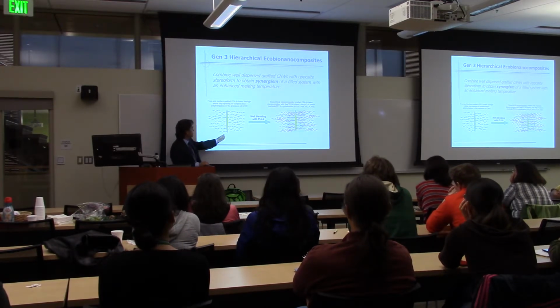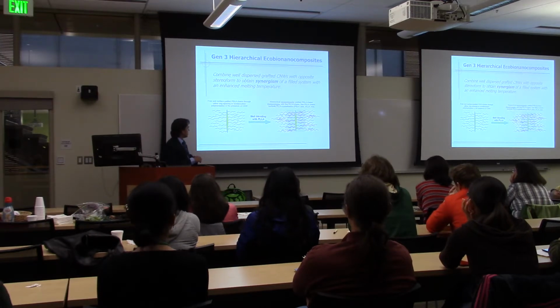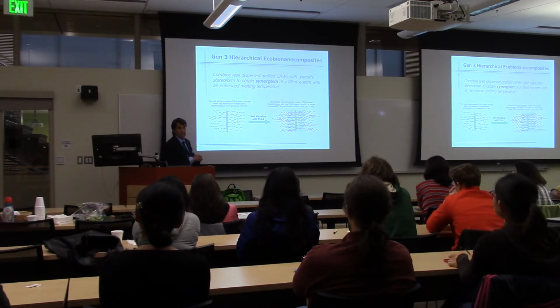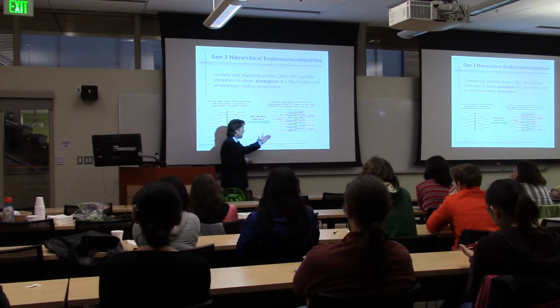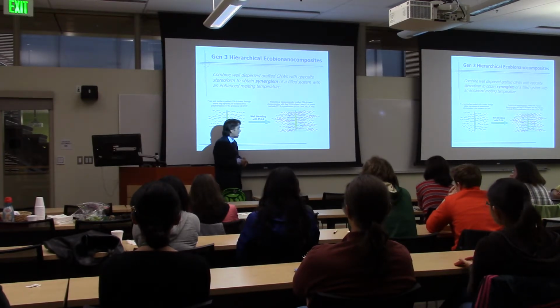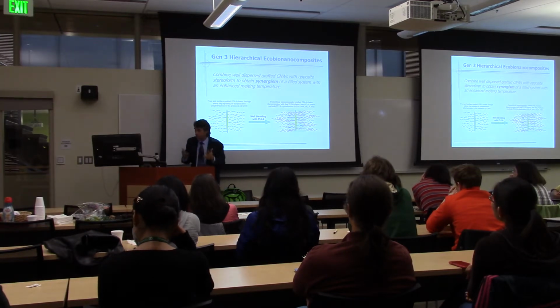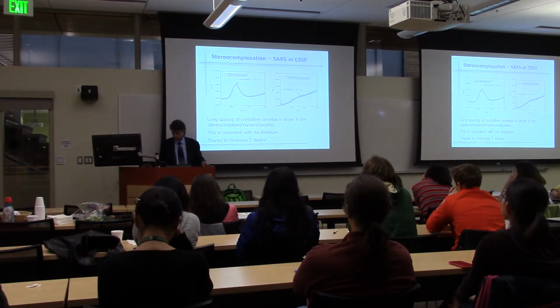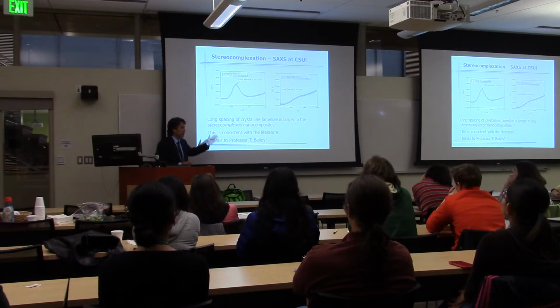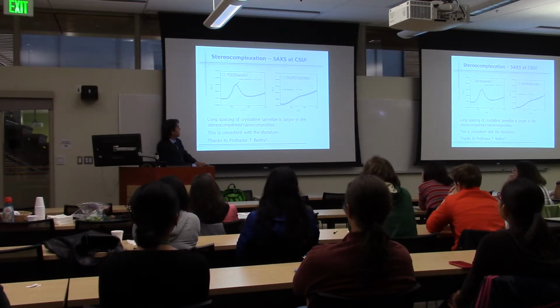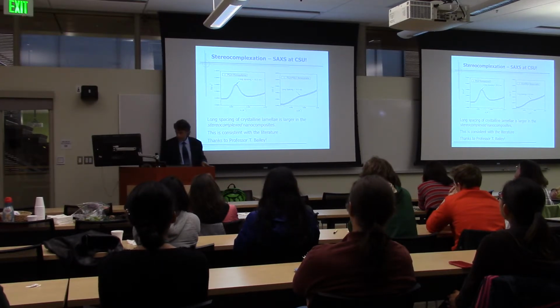So now I could decorate my chains, say with poly D lactic acid, and then embed them into poly L lactic acid, and I should form material with an even better melting point. Thanks to Travis here, we were able to characterize this using SAXS at CSU here, looking at the long spacing in terms of the crystallinity, and certainly this is consistent with the literature with what one expects to see when you do get stereocomplexation.